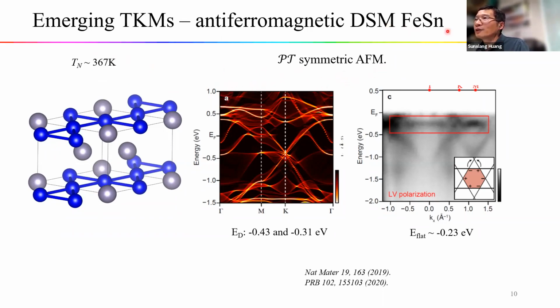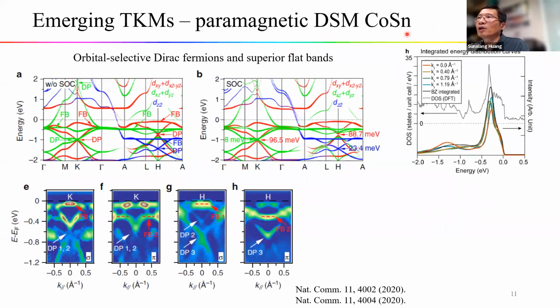So now let's quickly go through its sister compound, the paramagnetic Dirac metal cobalt-tin. In this compound, one interesting feature is that the band structure depends on the orbitals. In other words, different d orbitals give rise to quite different band structures. Interestingly, the flat band in these materials is rather flat and broad in momentum. There are a couple of flat bands as well as the Dirac points shown here. These general features have also been confirmed by the photoemission measurement. Because of the flat band, the density of states shows a large peak below the Fermi energy.